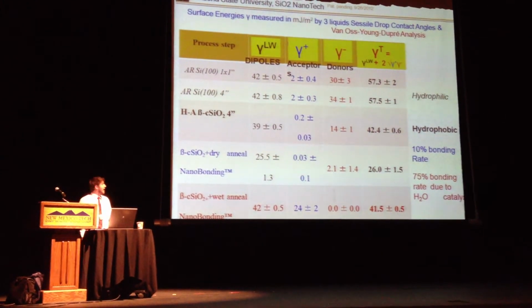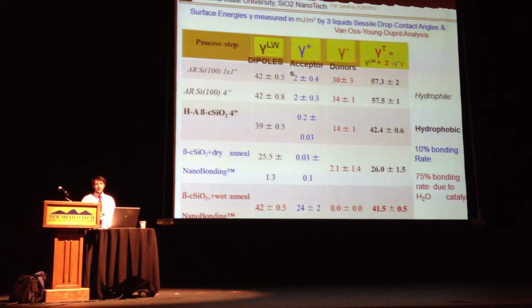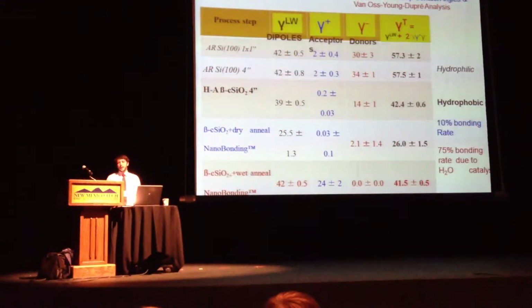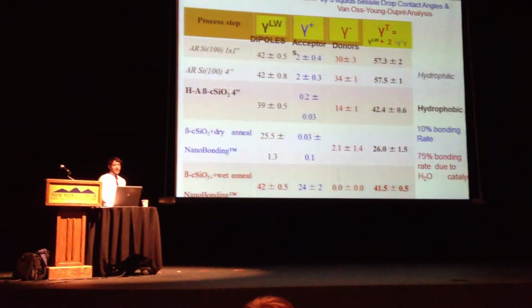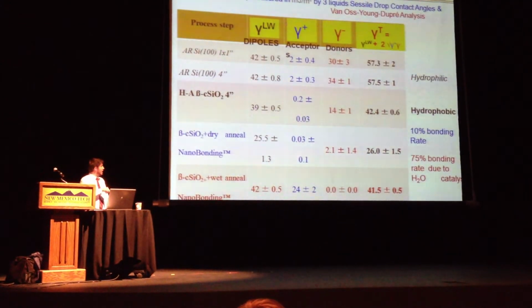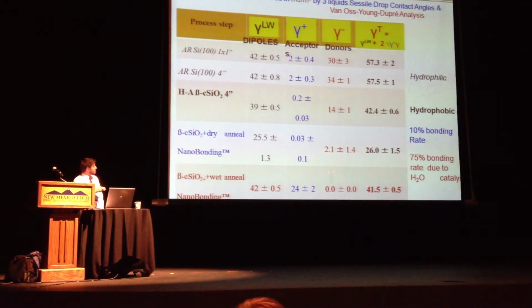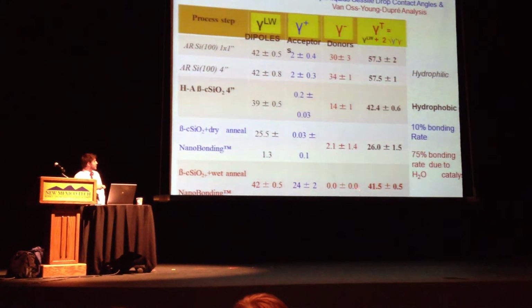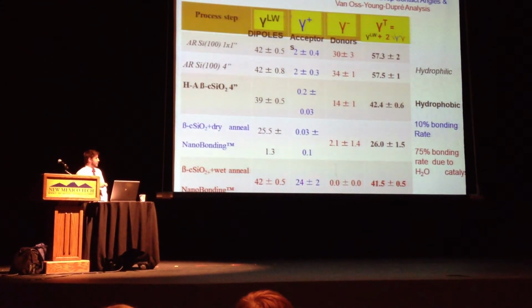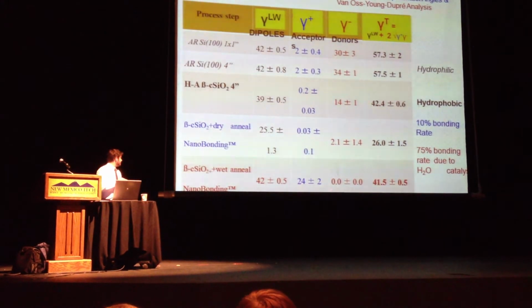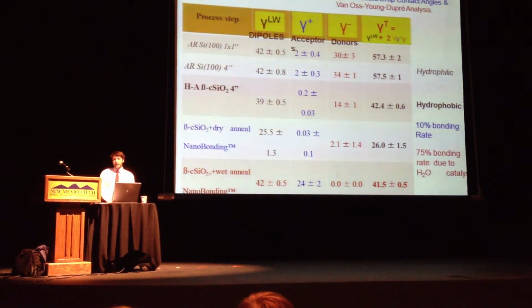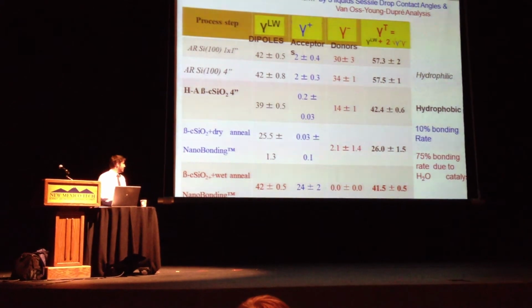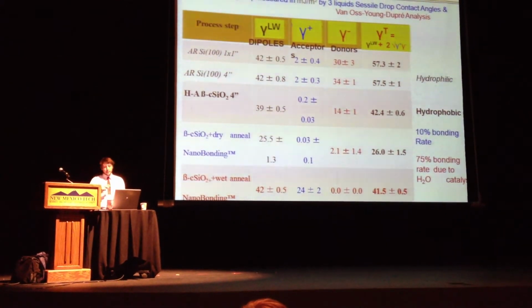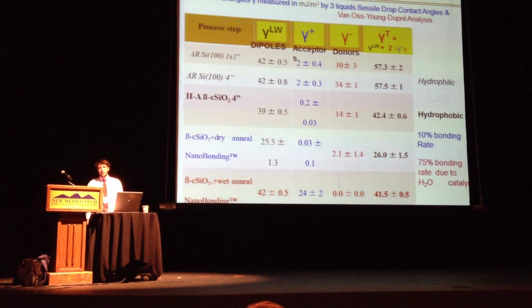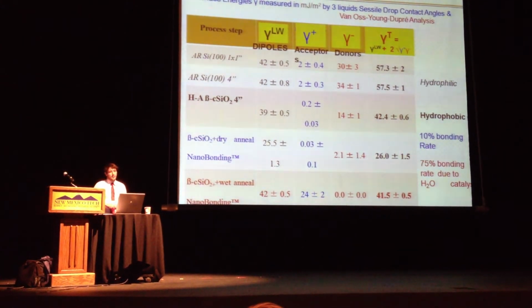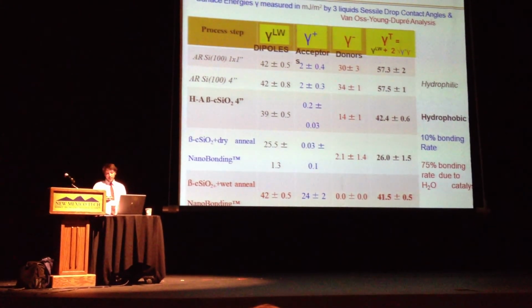What we can learn from that is understanding these surface free energies and what has changed. We can understand better what our surface needs for that bonding condition to occur. What we see is essentially an elimination of the donor component and an increase in the acceptor component of the beta cristobalite on the SiO2, and that is essentially the optimization of our bonding: the increase of acceptors and the reduction of donors for our surface free energy.